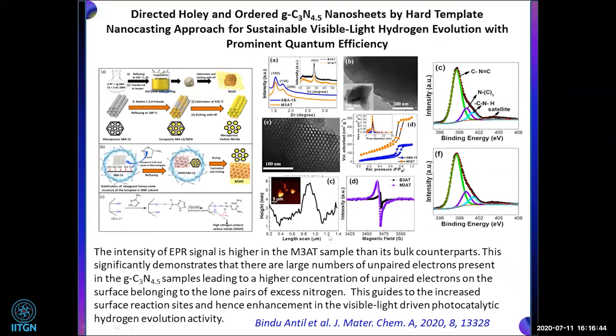Okay, so continuing with that one, this is just recently published, again on graphitic carbon nitride. Again, same story here. We got the same material, but the synthesis and the morphology of the material are completely different. This is a very nice nanosheet of graphitic carbon nitride. What we found is that π bonding at the sp2-hybridized carbon sites favors the clustering of the aromatic rings into the graphitic sheet.